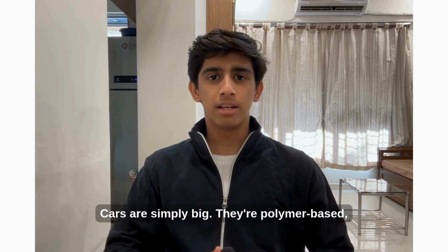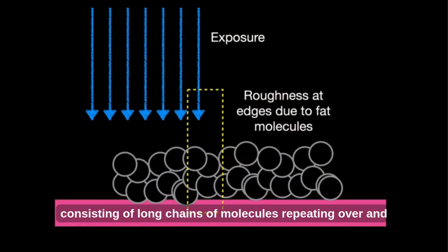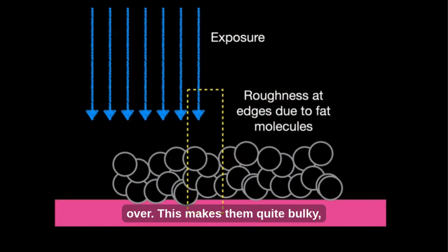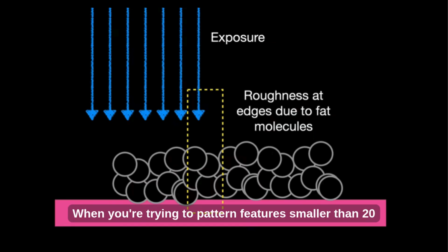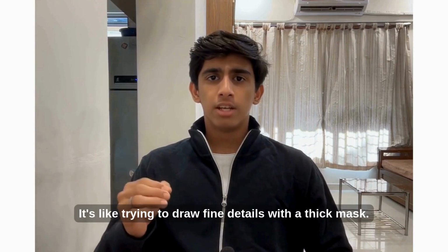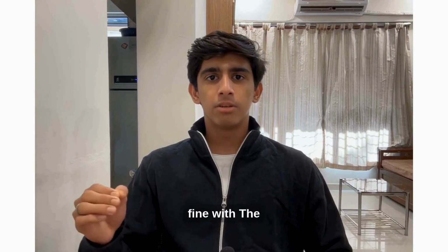CARs are simply big. They're polymer-based, consisting of long chains of molecules repeating over and over. This makes them quite bulky, typically about 3 to 5 nanometers in size. When you're trying to pattern features smaller than 20 nanometers, having 5 nanometer molecular building blocks creates inherent roughness and resolution limitations. It's like trying to draw fine details with a thick marker.